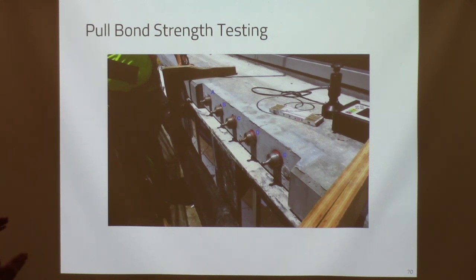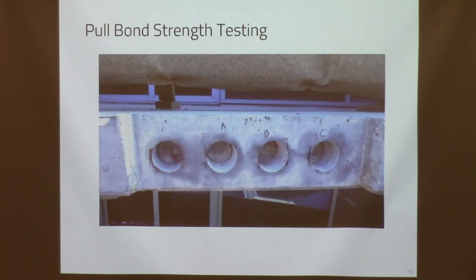And then they block that out, and you can see the concrete, the reason we didn't pour concrete all the way to the edge is when you do a pull bond test, it's very, very easy to get some unintended eccentricity that tends to put a little bit of bending in the surface, and so you don't get a real good accurate determination of the pure pull bond strength. So you want to make that as short as possible.